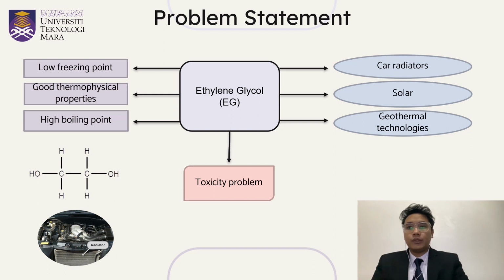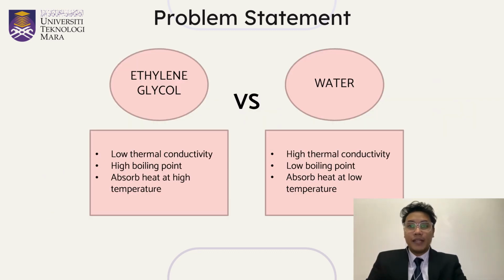Ethylene glycol degrades into harmful chemicals in the body. Ethylene glycol and its poisonous derivatives initially attack the central nervous system, then the heart, and eventually the kidneys. Based on studies by N.A. Usri, pure ethylene glycol has lower thermal conductivity compared to pure water. However, EG has greater properties in terms of boiling point, therefore EG can absorb heat at higher temperature than pure water. Nanoparticles aluminium oxide Al2O3 and silicon oxide SiO2 were added to overcome the disadvantages of EG.